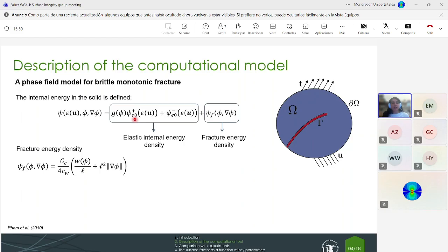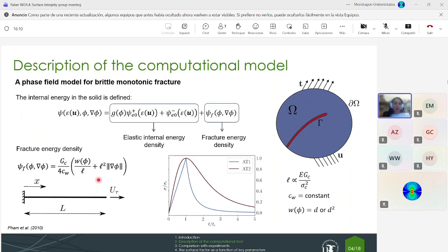Here we have a crack surface that is regularized. It is a region where there is a smooth transition. So this surface is defined using the phase field variable, as you can see here. We can find different proposals for the definition of these functions. The most famous ones are the AT1 and the AT2. So in the AT1 model, we consider an elastic threshold before the damage, and in the AT2 model, we consider the damage starts from the beginning. So in the community, we use one or the other one, depending on the approach that gives better results.